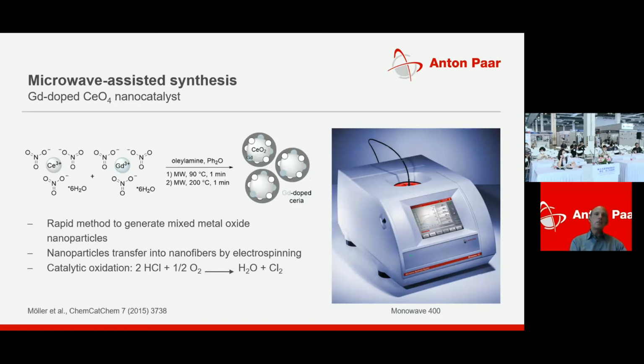The presence of gadolinium in cerium oxide helps to tune the capacity of this rare earth oxide to store oxygen. For the preparation, the proper amounts of cerium nitrate and of gadolinium nitrate were mixed in a microwave vial with some dispersant, which was oleylamine. Afterwards, using microwave assistance, this mixture was heated for 1 minute at 90 degrees Celsius. Then diphenyl ether was added to this mixture, followed by another minute of heating at 200 degrees Celsius.